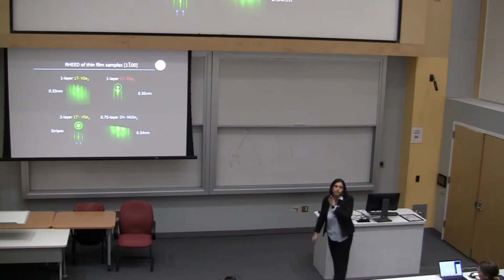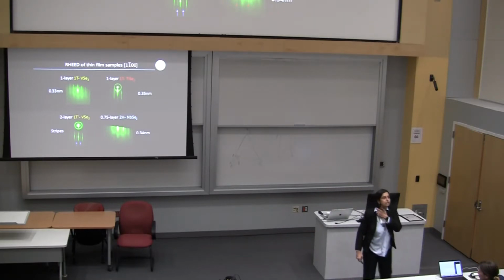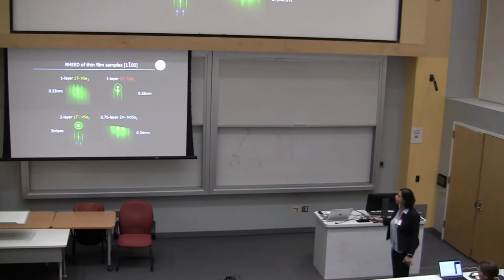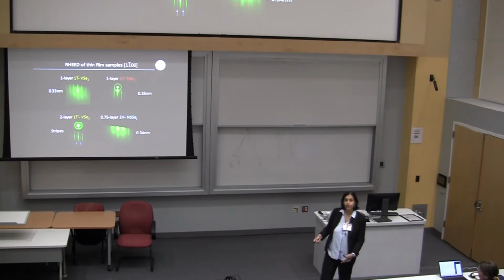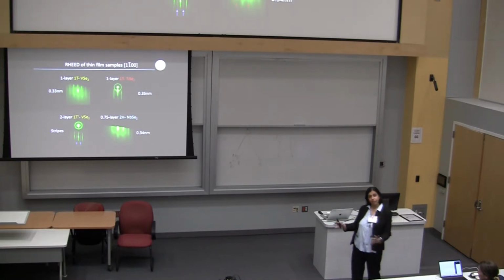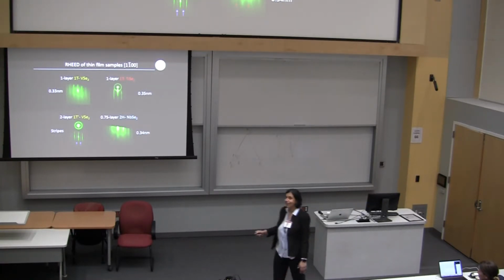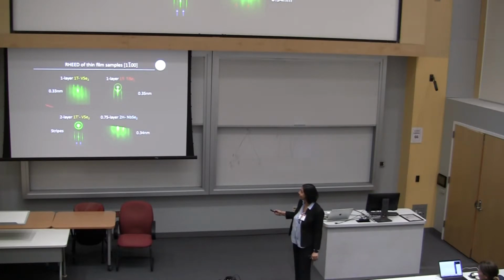Okay, so here are some examples of different RHEED patterns for different films. Vanadium diselenide, titanium diselenide, niobium diselenide, and these are two different polymorphs. One thing I want to point out is that their lattice constants are very, very close, 0.33, 0.35, 0.34. So simply by looking at the RHEED pattern of something, it's really hard to tell. You better be evaporating the right compound because you can't tell by looking at the RHEED pattern. However, you can see all of these streaks.